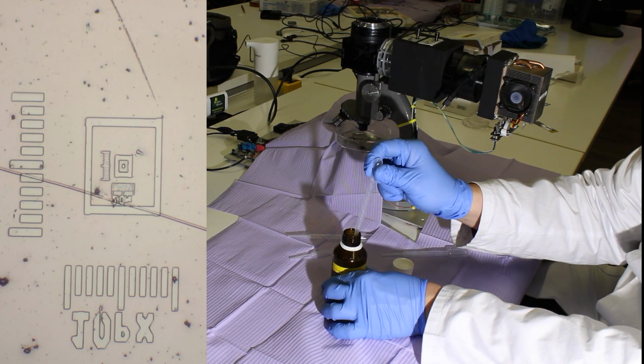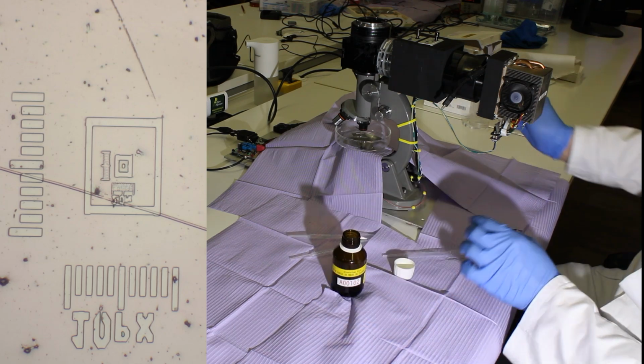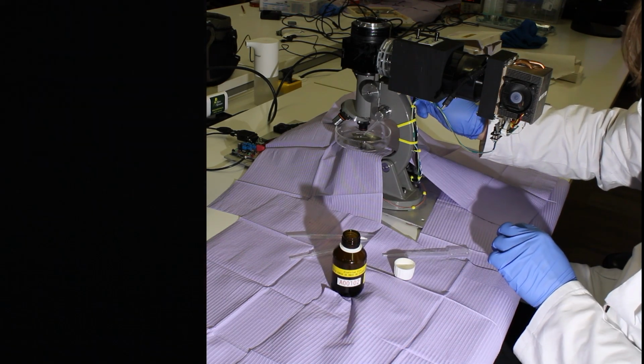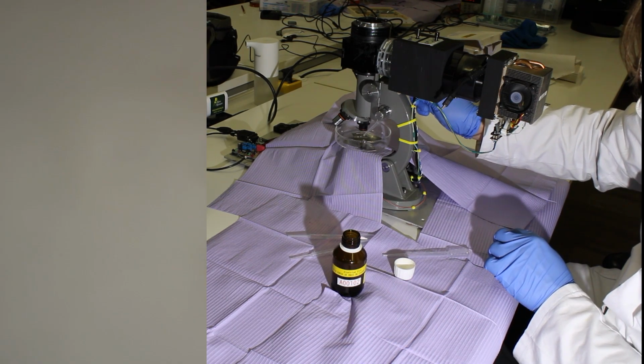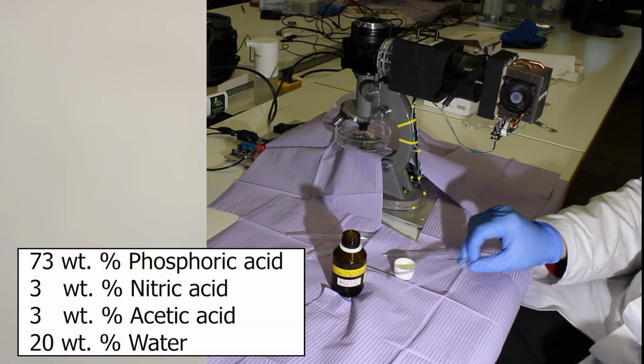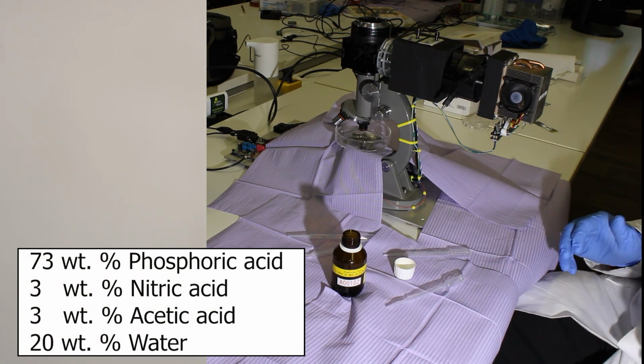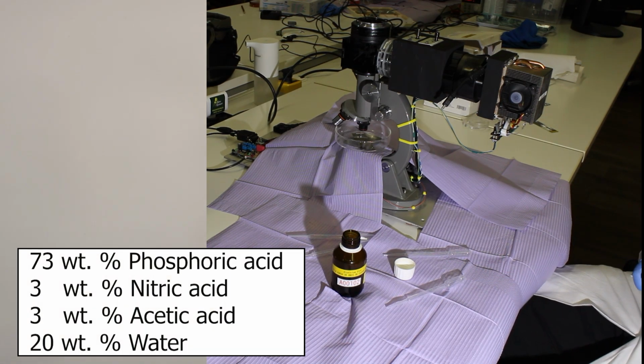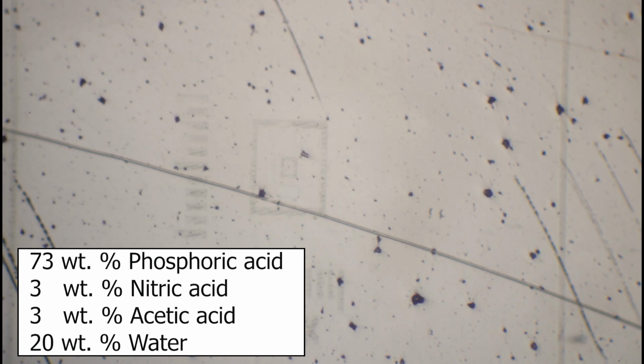To transfer this pattern to the aluminum layer, I apply an etchant, which is a mixture of phosphoric acid, nitric acid, acetic acid, and water, where the phosphoric acid makes up the bulk and serves to remove the aluminum oxide. The nitric acid oxidizes the metal to the oxide, and the acetic acid is a surfactant. We can see that while the acid is working on it, the image slowly reappears.